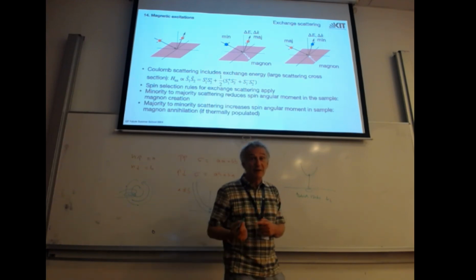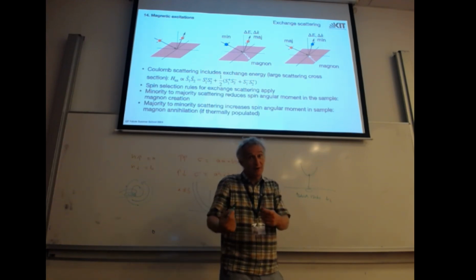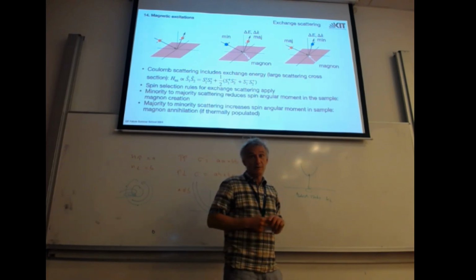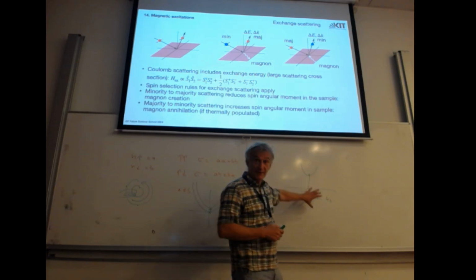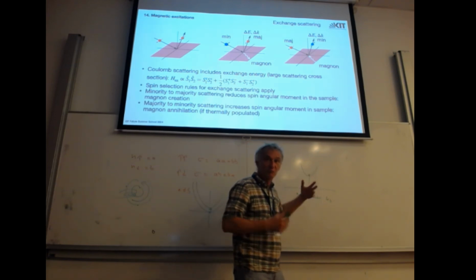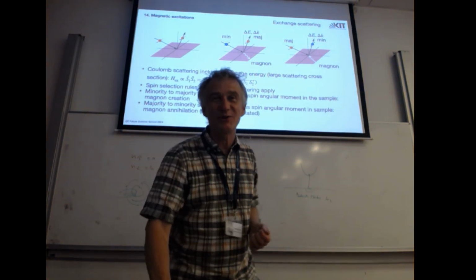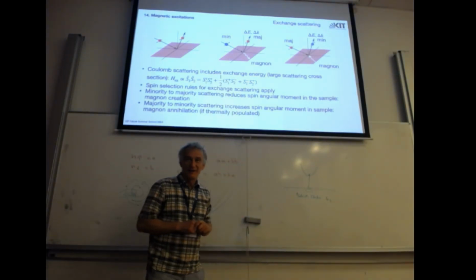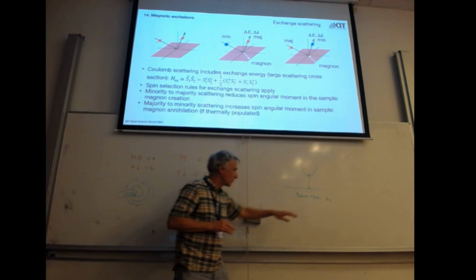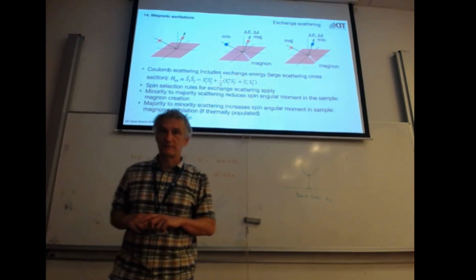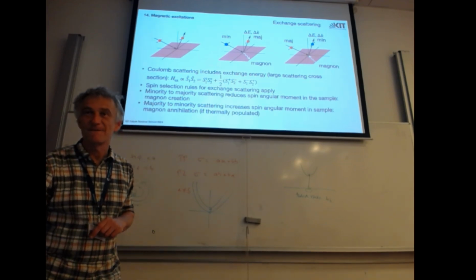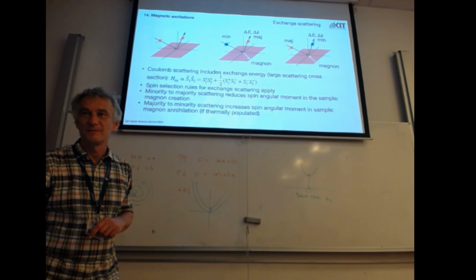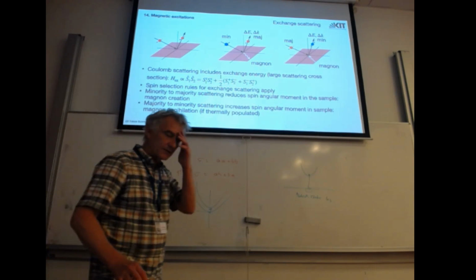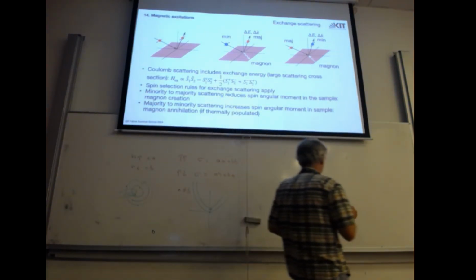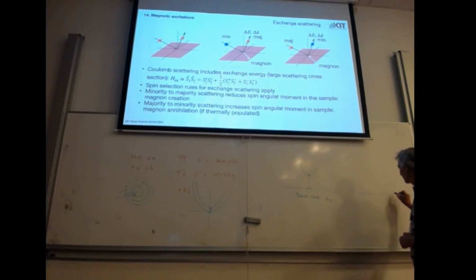And in the scattering process, it has to go again to another Bloch state. So there is an intermediate state in this process, and the intermediate state is short-lived, so there will be an energy broadening, but the K parallel nevertheless needs to be conserved. Well, again, then it means that it's conserved up to the broadening of the energy level of this intermediate state, right? Yeah, the broadening. So this is a state. So how should I draw this?